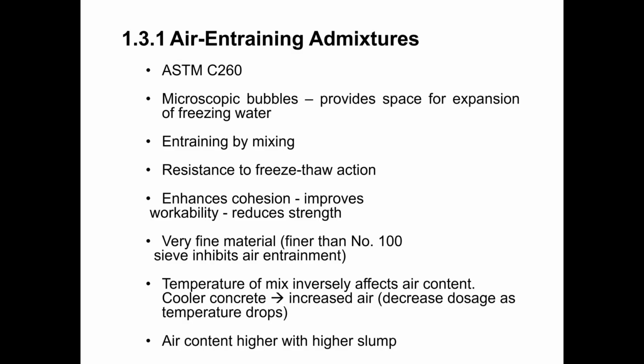The temperature of the concrete mix generally inversely affects the air content. So as temperature goes up, you're going to get less benefit from your air entraining admixture. So if a plant has a standard mix that they use throughout the year, that's an air entrained mix, what they may find is that in the summer months, they have to use more air entraining admixture in order to achieve the desired level of air entrainment. So as fresh concrete temperature goes up, the effectiveness of the air entraining admixture goes down.